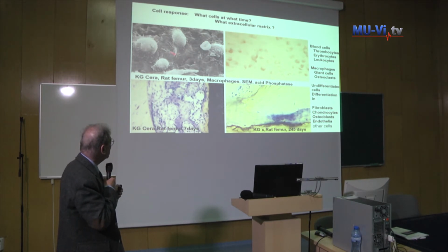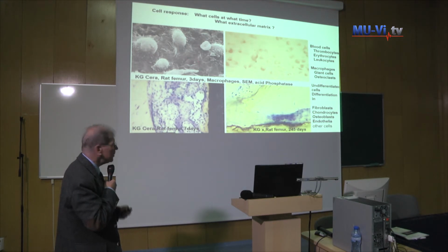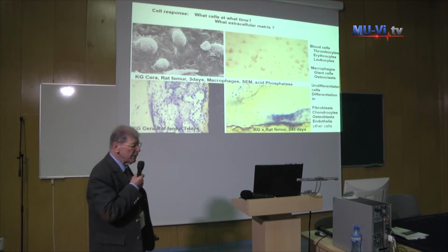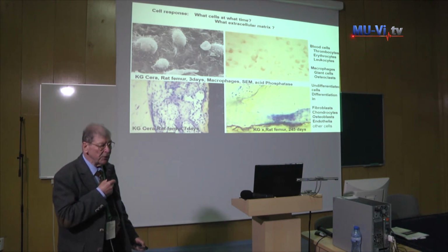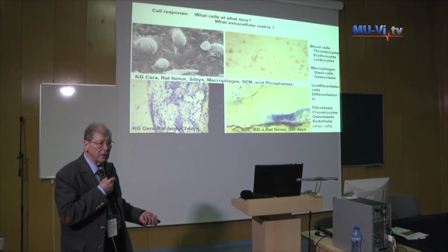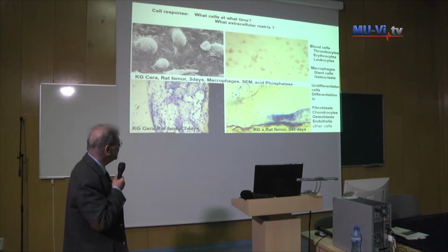They change the surface. The macrophages display acid phosphatase, as you see here, and after 7 days there is already bone at the surface, so all these macrophages disappeared. Why they disappear and what they released in the time and at the surface is not yet clear.